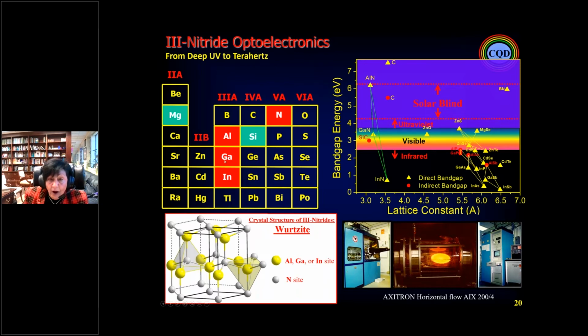And now if we come with gallium nitride, and with the gallium and indium we make alloys, binary, ternary, or quaternaries, we can change the energy gap, and we can make the lasers and the detectors from the deep UV, 6 electron volt, 200 nanometer, to the end of the interband or intersubband, going up to the terahertz.